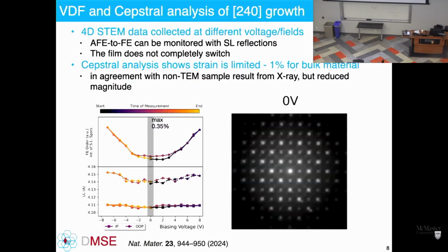But what we can measure then from these diffraction patterns are the lattice constants, as well as the ferroelectric order, through the strength of those satellite reflections disappearing. So in other words, we become ferroelectric over here. You'll see these reflections disappear, and then they come back as we go towards 0 volts and back to -10. They disappear again.